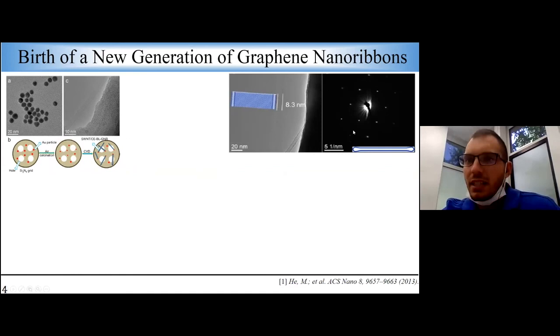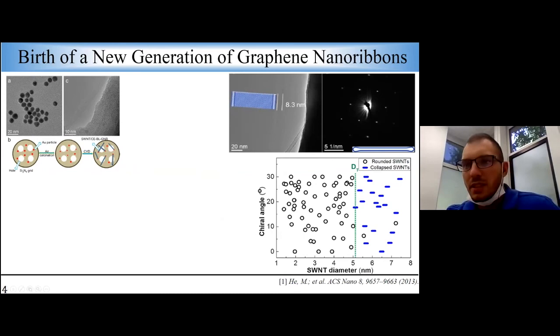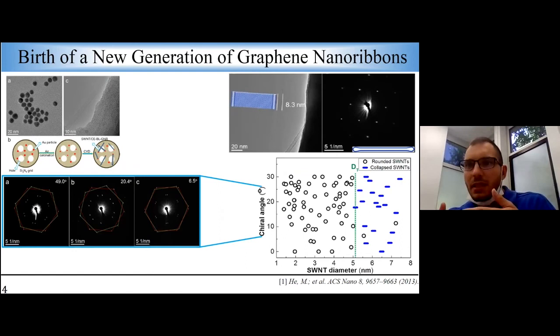Also, the experimentalists have reported a correlation between the chirality of the nanotube, the corresponding stacking sequences and the nanotube diameter, observing that all resulting samples automatically collapse after overcoming a given threshold of the diameter, which is nearly equal to 5.1 nanometer. And it looks like this collapse threshold diameter seems to be slightly dependent on the specific lattice stacking combination between facing layers.